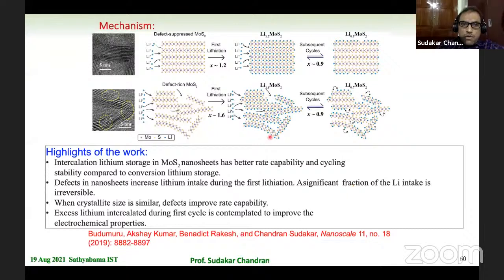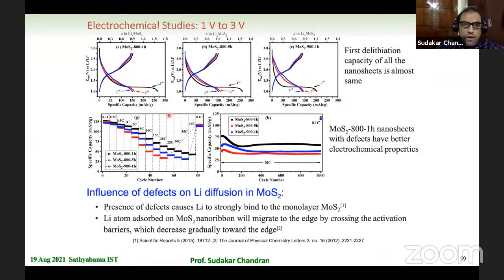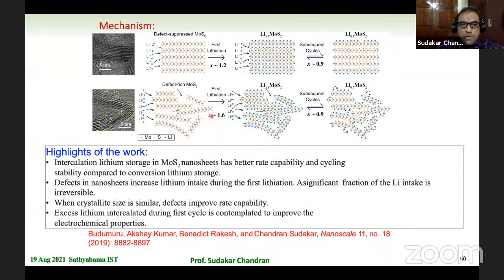Of course, the reason for the increase in the rate capability can be understood from this simple mechanism that we proposed. Wherever the defects are large, we found large lithium intake in the beginning. X is as high as 1.6, even sometimes 1.2 we have found it takes up, but after that the cycling is roughly about 1 lithium back and forth. So the extra lithium that goes in is sitting somewhere at the defect sites, and it helps to make the lithium diffuse much more easily.